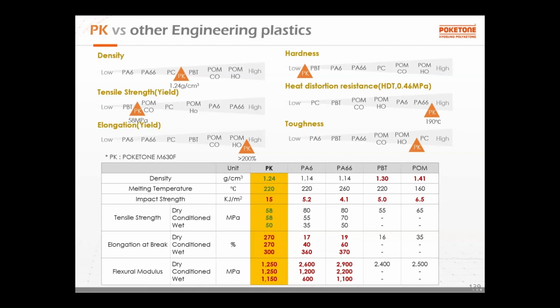In the bottom table, we can see two points. One is impact strength, and the other is the changing properties of nylon. Polyketone as unfilled base resin is 15 kilojoule per square meter, versus nylon 4 to 5, PBT 5, POM 6. So three times higher as unfilled base resin. Nylon is a very good material, but it absorbs water and changes a lot. As dry 17, 19, but after wet 360, 370, but polyketone 200%, always stable.